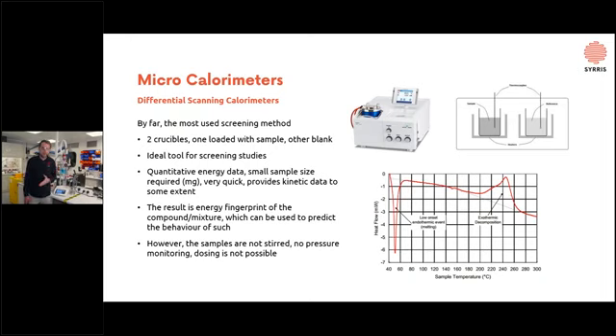So the left one is actually the endothermic effect of melting of the solid substance in the sample crucible. And the peak on the right, the broad peak, is actually the onset and actual decomposition of the sample. So you can see this is the kind of data we are able to get with differential scanning calorimetry, but it lacks all the necessary information to do the proper safety studies. So that's why I mentioned we need the combination of the three to get comprehensive information.